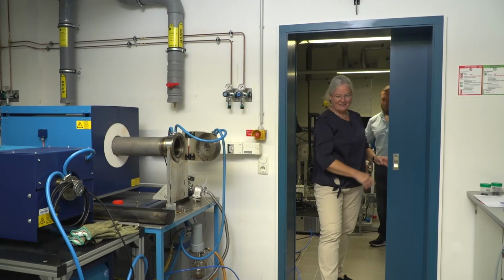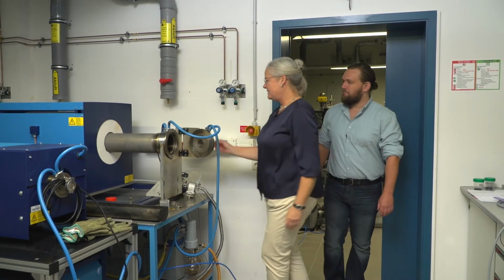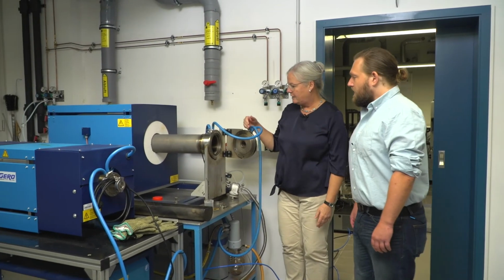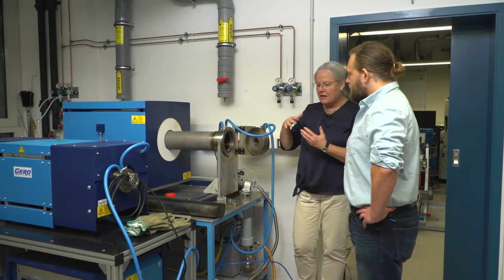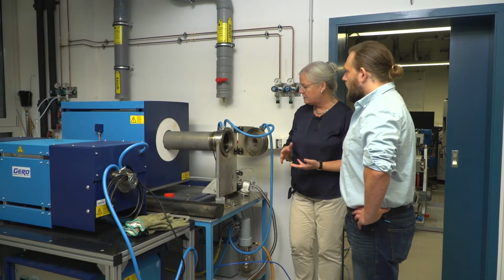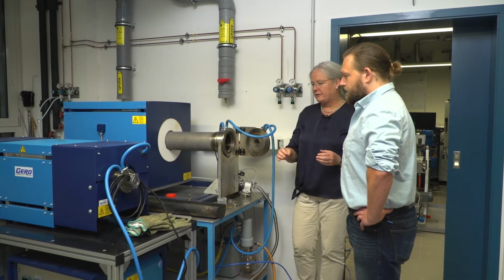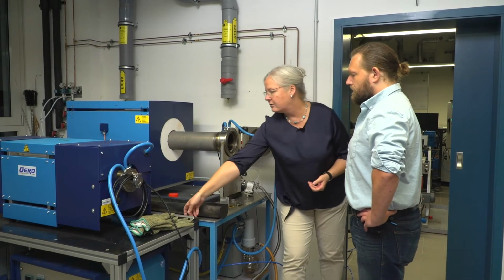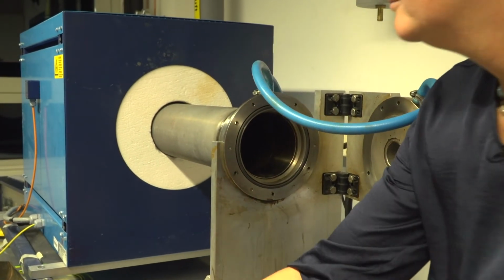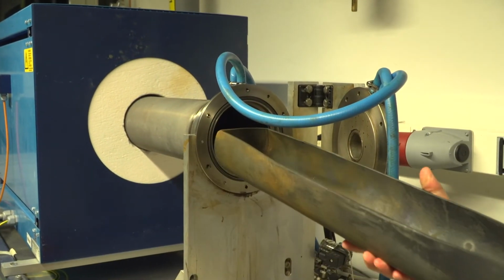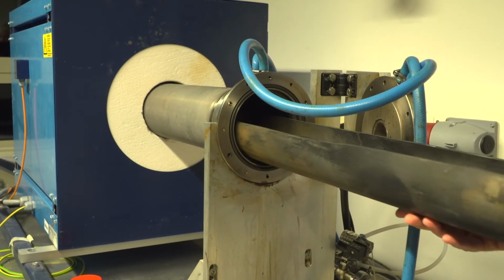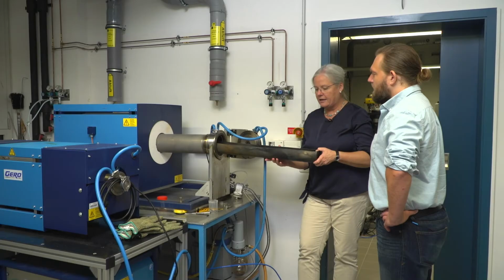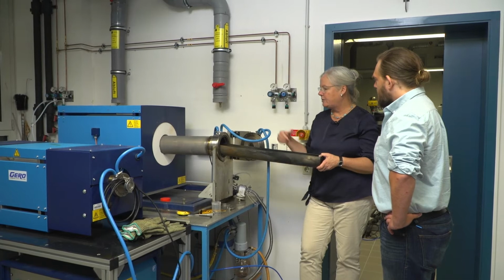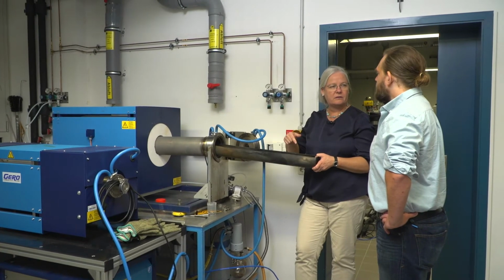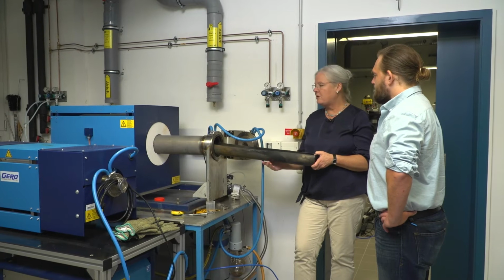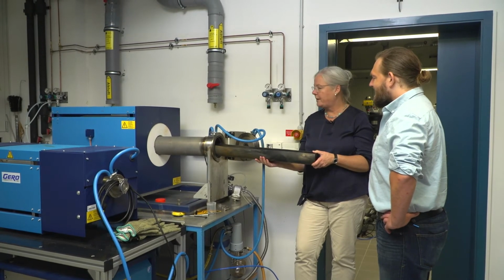So come in here. We have here our furnaces, and these are two of them. And this is a bigger one we use for bigger samples. And this is only for testing. And we have here only a boat, crucible. And here we have a bigger boat, and we can put samples in this boat. Put the boat in there. But you have to take care because the temperature is not always the same along the length. So we measured everything, and we know at which place, which temperature.